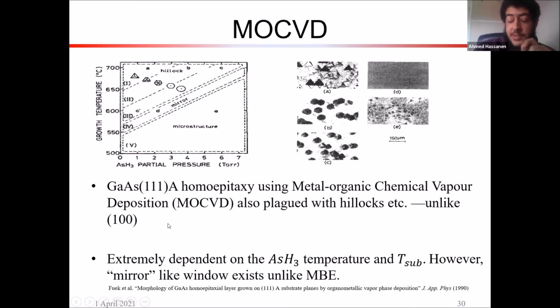But interestingly, unlike MBE, we have this window of smooth growth that we can access here. So if you can see here, this is the arsine partial pressure, and this is the growth temperature. No matter what conditions you pick, you get hillocks and defects everywhere. But if you pick the right arsine partial pressure and the right growth temperature, maybe you can fall into this smooth region, which doesn't exist in MBE. And so, okay, that's interesting.